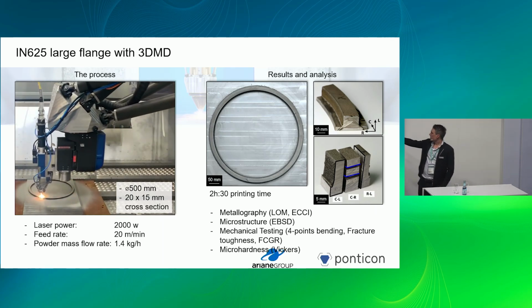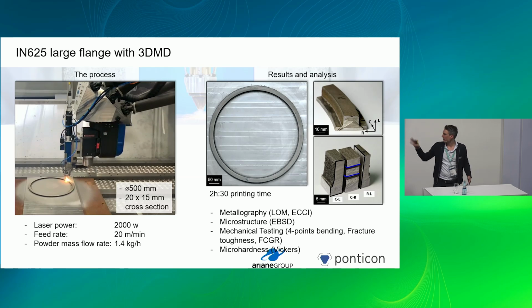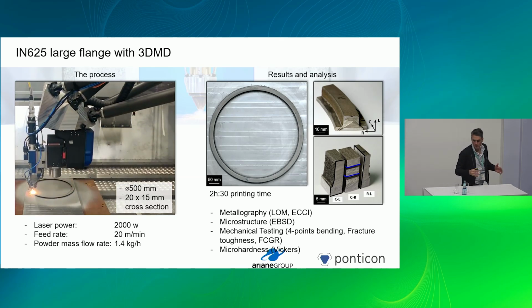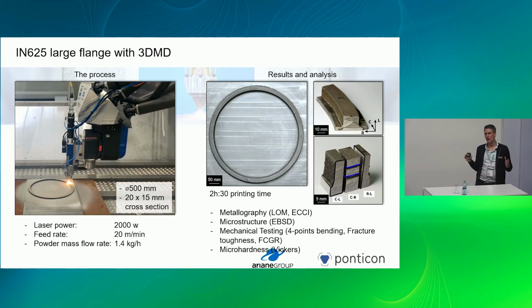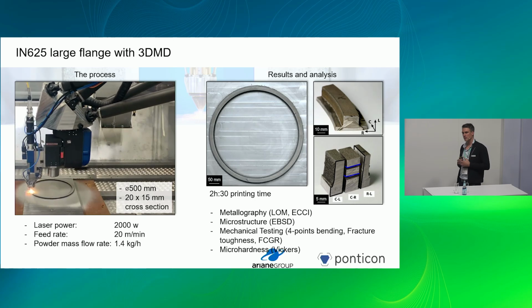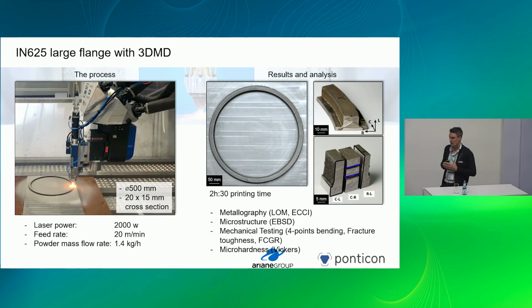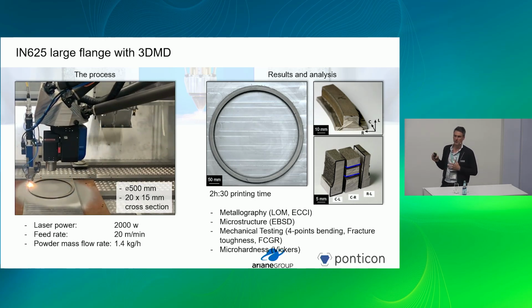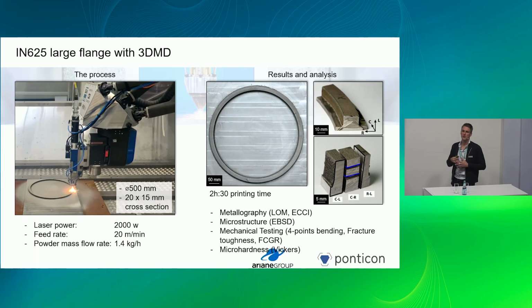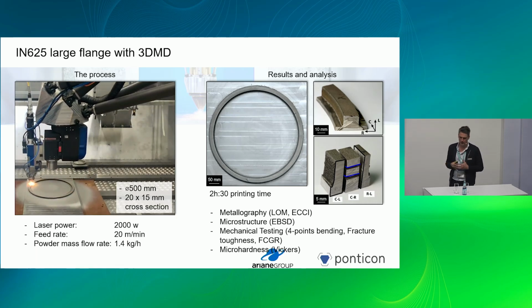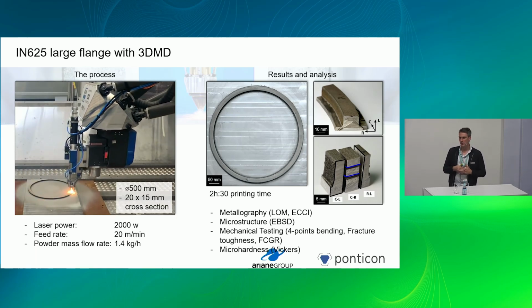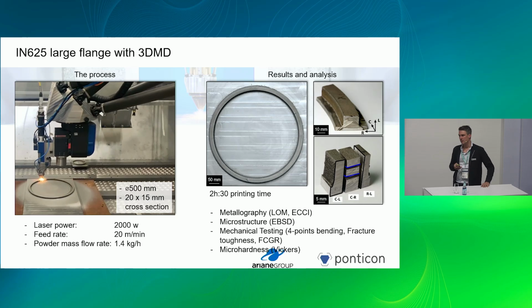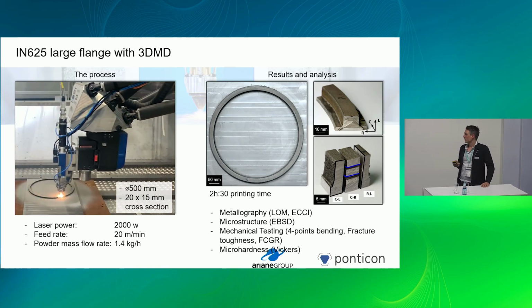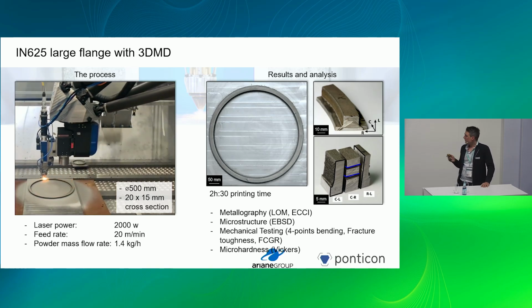And then for this deposit, I think the picture doesn't really do justice to the real part. It's 0.5 meter in diameter, 20 times 15 millimeters in cross section, and the deposition time for that was only 2 hours 30 minutes. So if you do this in powder bed fusion, it takes significantly longer, and also if you go for conventional DED, processing time would be significantly higher.